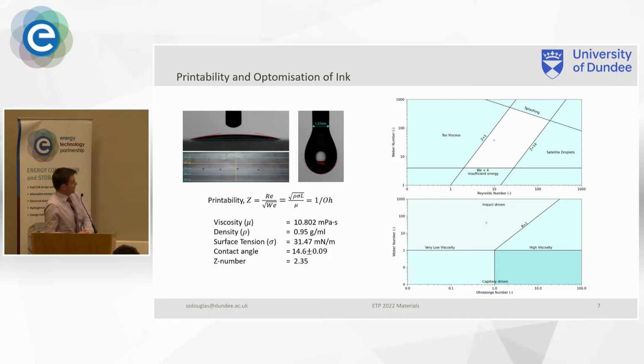And then those numbers are values I measured by measuring the viscosity, density, and surface tension of the ink, which gives that Z number 2.35, which is between the 1 and 14, so it's a printable ink.